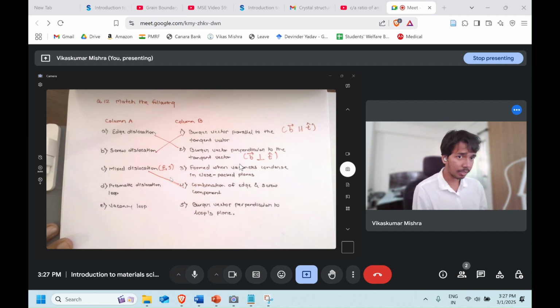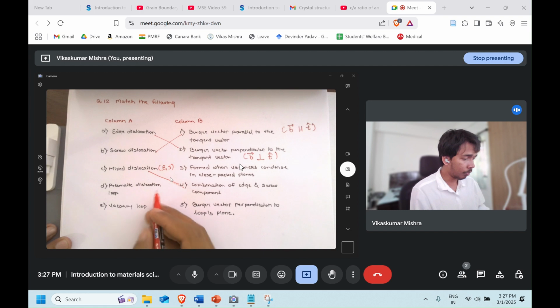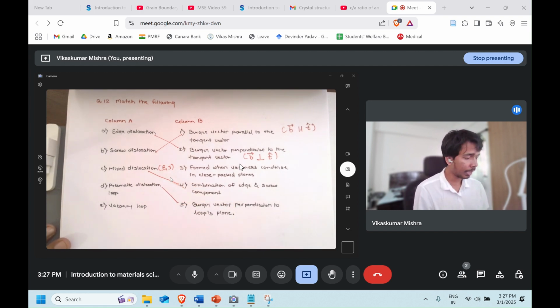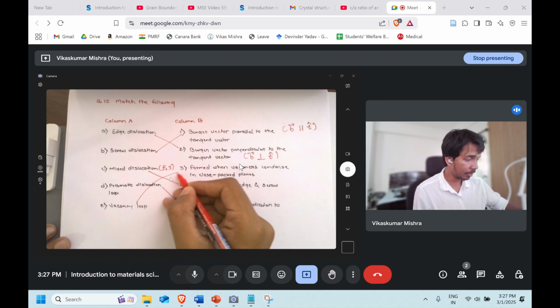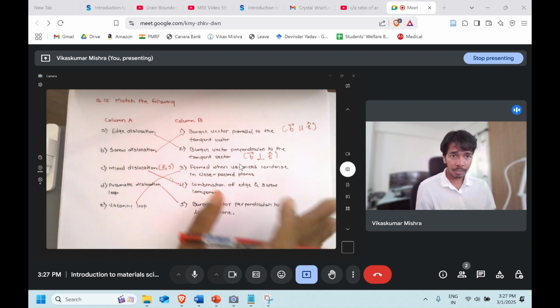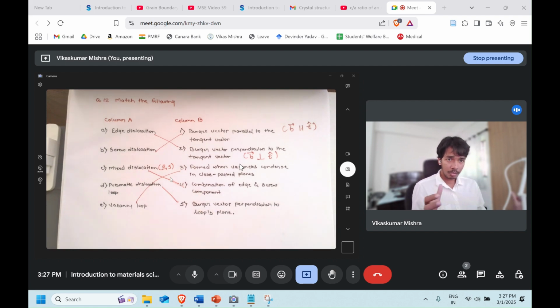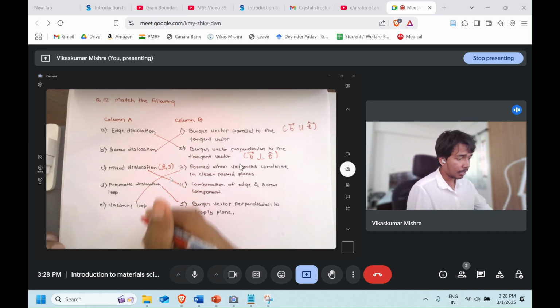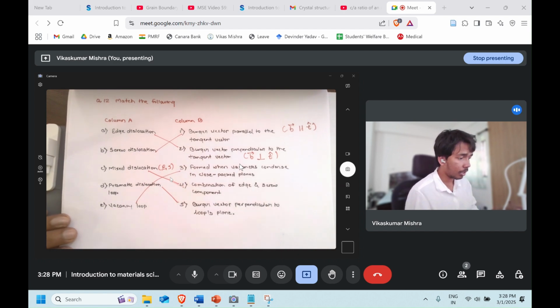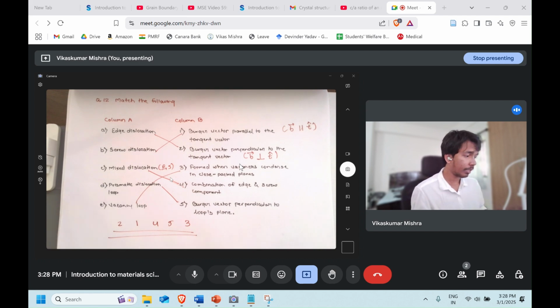Prismatic dislocation loop, we just now discussed that. In the prismatic dislocation loop, the Burgers vector will always be perpendicular to the loop. So Burgers vector perpendicular to the loop plane. So D will match with the 5. And a vacancy loop forms when the vacancies condense in the close packed structure. So we can say that E will match with the 3. If we take a plane and we condense a lot of vacancies in that plane, they are coming together, then we can say that they are forming the vacancy loop. And that's why we can say that option E will match with the 3. So the correct answer is 2, 1, 4, 5, and 3. Okay, let's move ahead.